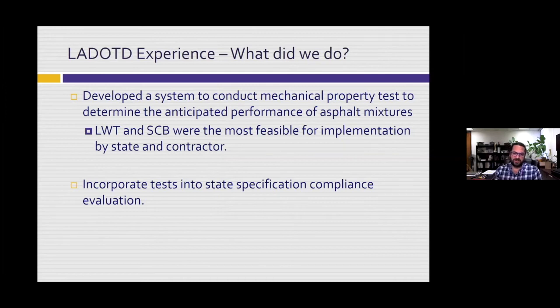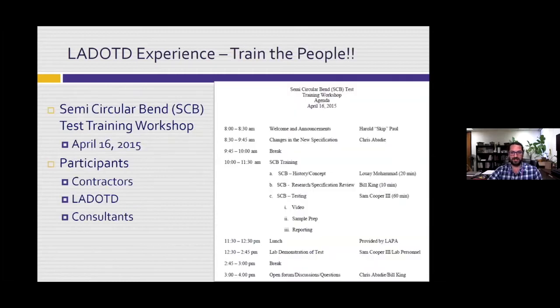So in Louisiana, we developed a system to conduct the mechanical property testing based on the performance or anticipated performance of asphalt mixtures. And again, that's based on laboratory test development and correlating that to field results. And that's really where an agency has to be confident in their data and reviewing it and their performance data as well. And LWT and SCB were the most feasible for implementation in Louisiana by both the state and the contractors in the state. And then we incorporated these tests into the specification compliance evaluation.